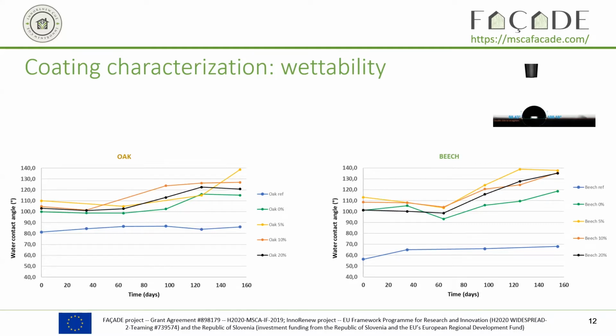it's with weathering, but inside. So we have samples outside on the roof, and we have control samples inside in the lab. And every month we are measuring the water contact angle for the samples outside and for the samples inside. These are the samples inside. For the samples inside, for the reference, for the two different woods, the water contact angle is stable with time. And you can see that for all the others, even for the coating at 0% without biocarbon, you have an increase, a slight increase of the water contact angle over time.